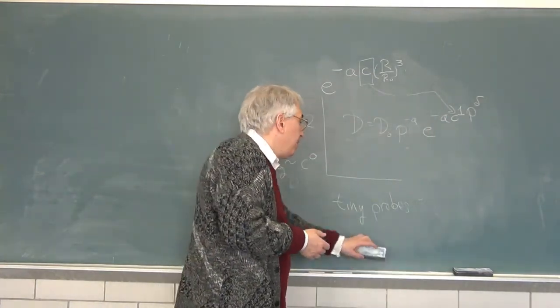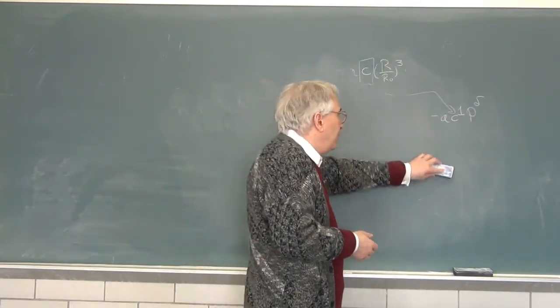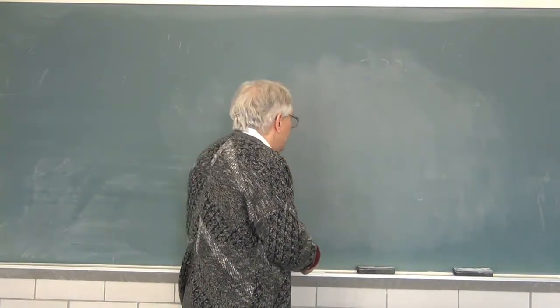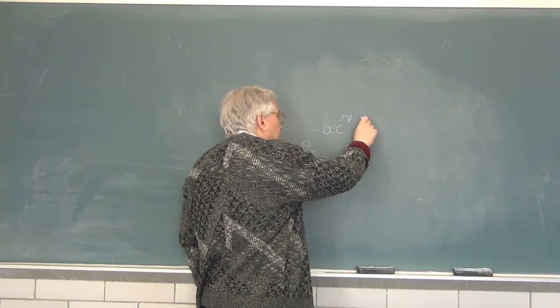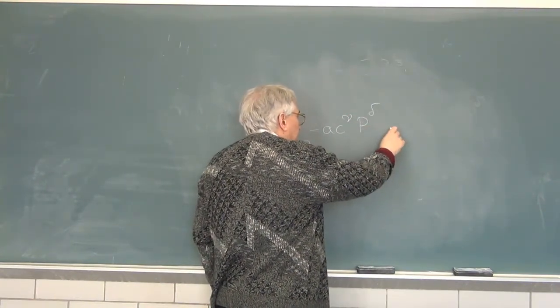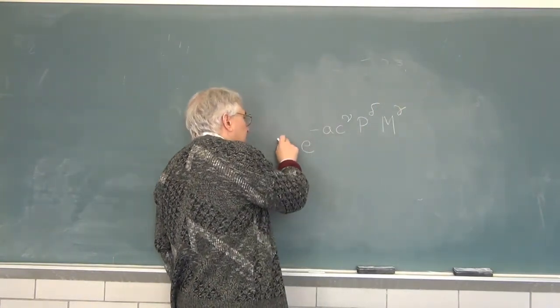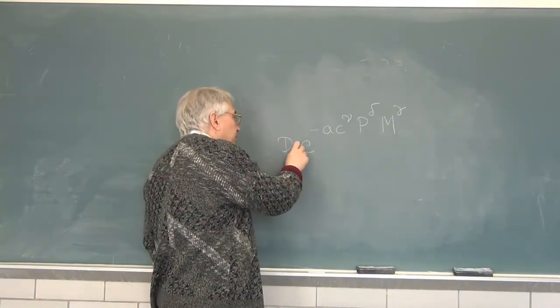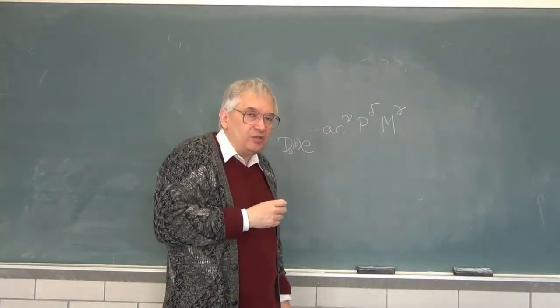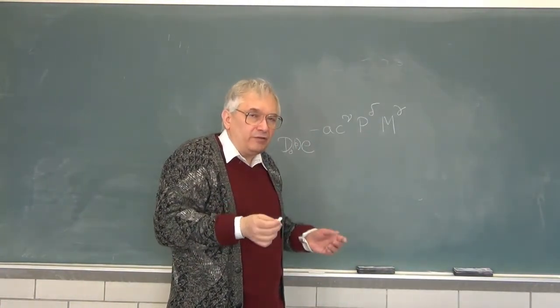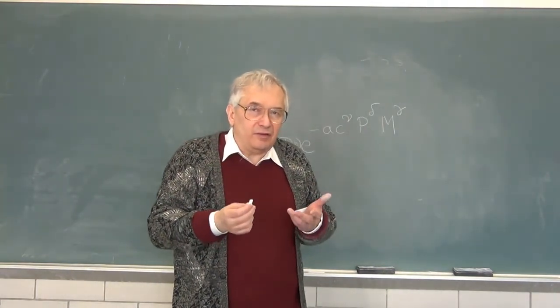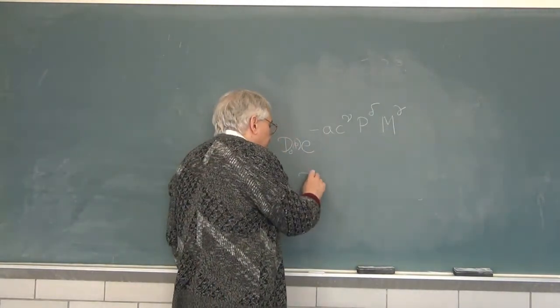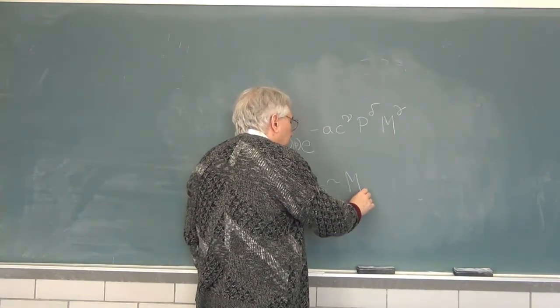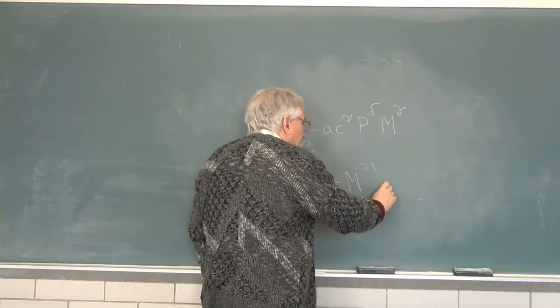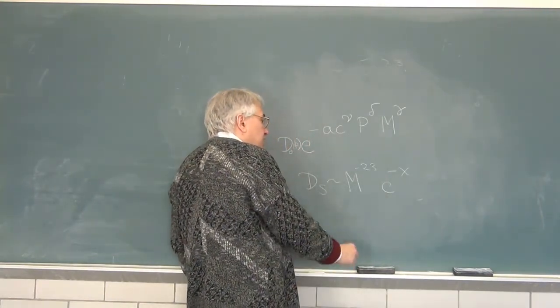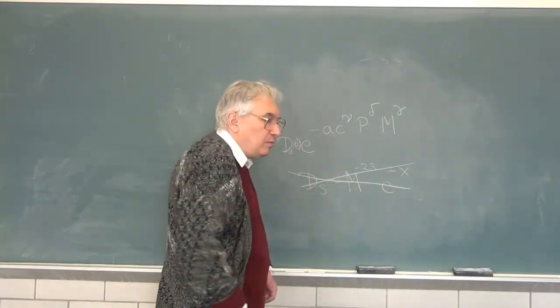And throughout, in almost but not quite all cases, we found that a joint stretched exponential, e to the minus a c to the nu, probe molecular weight to some power, matrix molecular weight to some power, d0, which has to be separate for each probe. This functional form describes polymer self-diffusion. There is almost never any evidence for scaling behavior in which the self-diffusion coefficient goes as, for example, Ds proportional to M to some power, like minus 2 or minus 2.3, c to some power x, where you can put in such x as you want. Scaling behavior is simply not found in polymer solutions.